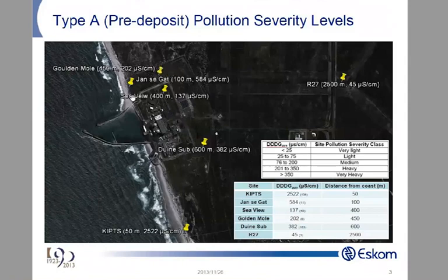Now you can see here where we got Sea View, which is, I mean, Robbie Watson, my sidekick, comes up with these amazing names. But okay, Sea View here is 400 meters away, and we've got 137. 137, we're coming here to medium. My goodness, extreme down to medium. And 2 kilometers inland, 2.5 kilometers inland, light. In the same area. And now if you had to work on these results here, what would you have done?